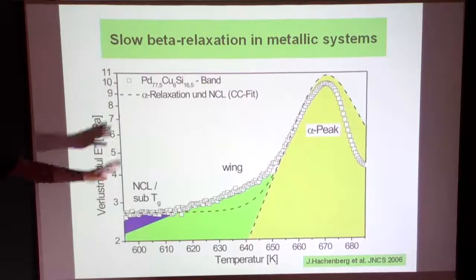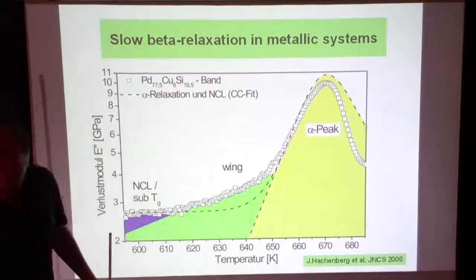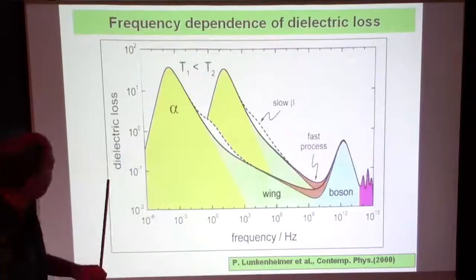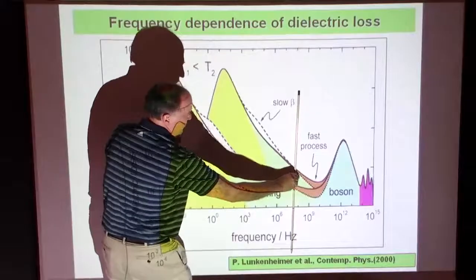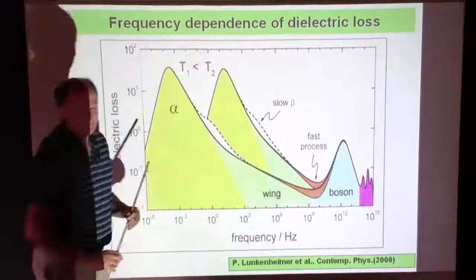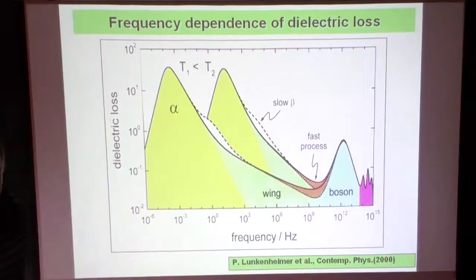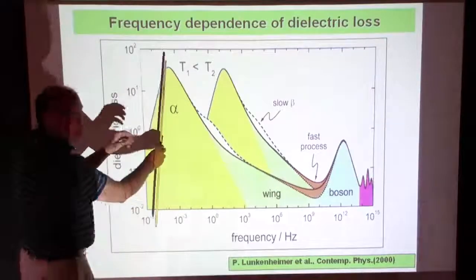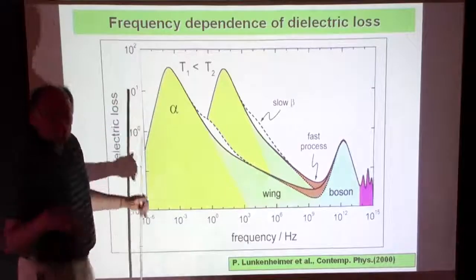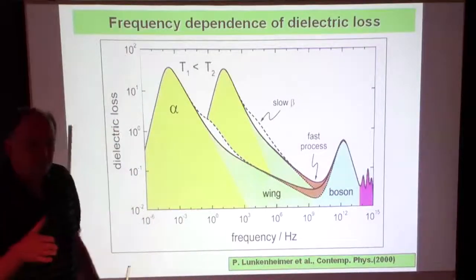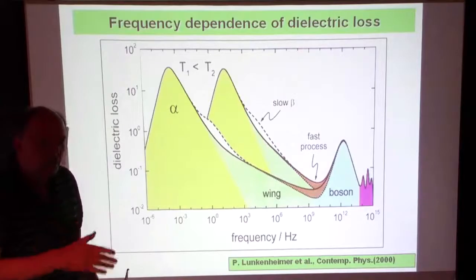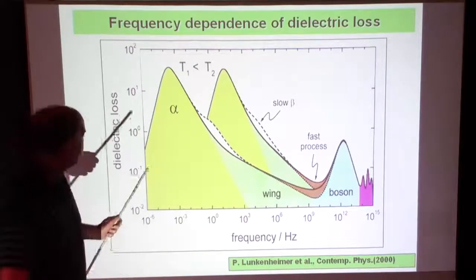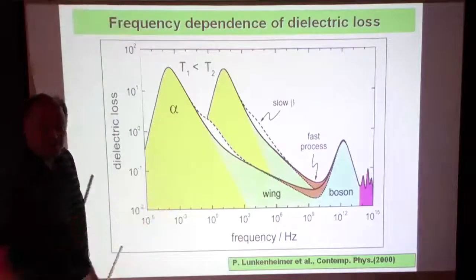It's 50 hertz. Okay, and you shift with your frequency. If you're sitting here, for example, at high frequencies, megahertz or something, you're shifting your whole spectrum through that frequency by temperature. You're not tracking the peak. I can track the peak also, okay? This is what we can do actually, but it's not necessary. You fix the frequency and shift the temperature, or vice versa. Fix the temperature and vary the frequency.